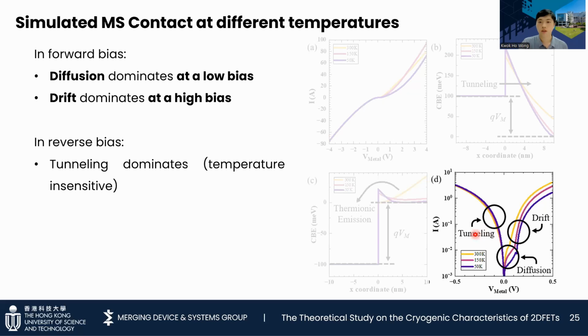The switch in the conduction mechanism can be more easily seen when we plot the low bias region of the IV characteristic in a log scale. We clearly observe two different conduction mechanisms, of which diffusion dominates at the low bias region, while the drift mechanism plays out at the higher bias condition. The diffusion current decreases with the reduced temperature due to the higher potential barrier and lower thermal energy, so that the number of electrons able to overcome the barrier also reduces.